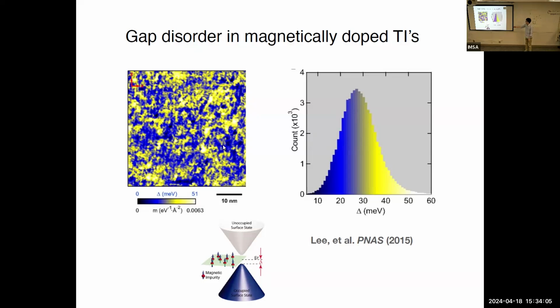And the range is actually very large. It starts all the way from a few milli electron volts to up to 50 or even 60. So we've seen this work and decided, can we actually model our response to see if any kind of this disordered gap distribution can fit our data?